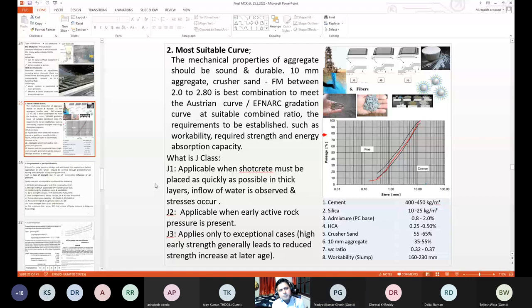This is the mix which is precisely done. The admixture is recommended at 0.8 to 2%. The HCA, hydration control additive, 0.25 to 0.50%. The crusher sand at 55 to 65% will be good if your target is to achieve 38-35 MPa of strength, and the 10 mm aggregate should be 35 to 55%.